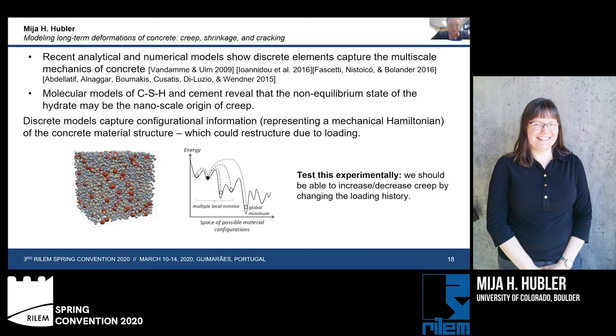The next point is that some molecular models of the calcium silicate hydrate and the cement reveal that the non-equilibrium state of the hydrate may be the nanoscale origin of the creep. Okay, so what is unique about discrete models and why do they capture this multi-scale mechanics so well? Well, the thing that's different about discrete models is that they capture configurational information. This represents the mechanical Hamiltonian of the system. Or in other words, the concrete material structure itself is captured in this model.